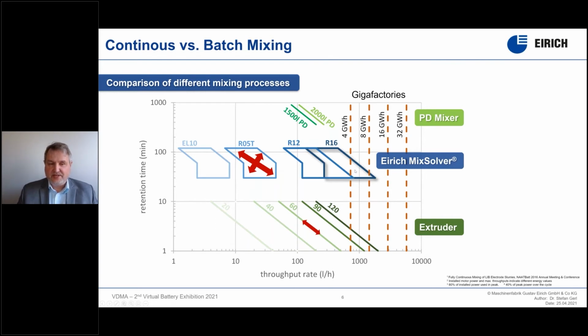We have different sizes of machines, and if we look at the currently planned gigafactories, which are in the range of 4, 8, or 16 up to 32 gigawatt hours, we see that with our machine named R16, 900 liter capacity, we can match with one machine the 8 gigawatt hour capacity. With an R12, which is a very common machine at the moment, we can go to 4 gigawatt hours with one machine. And so we are well prepared to go for the high capacities.